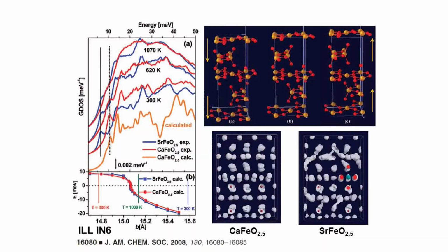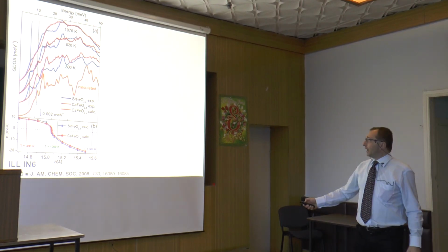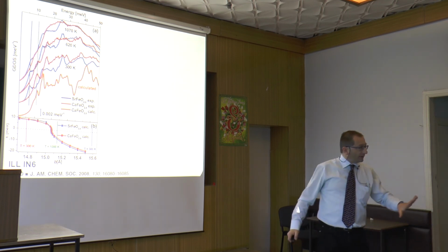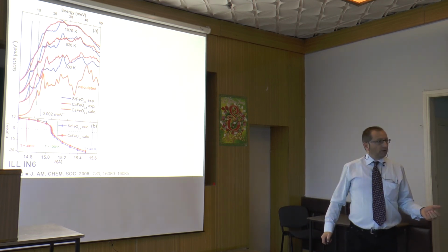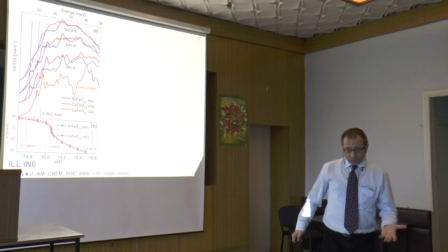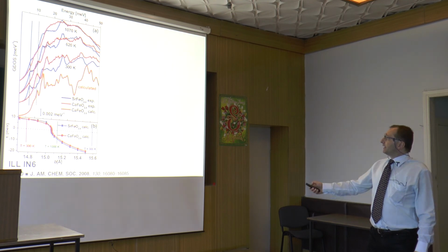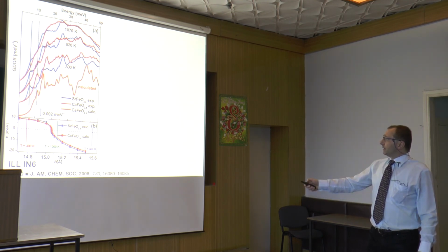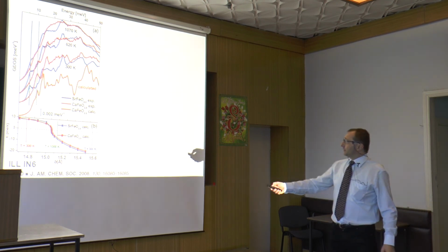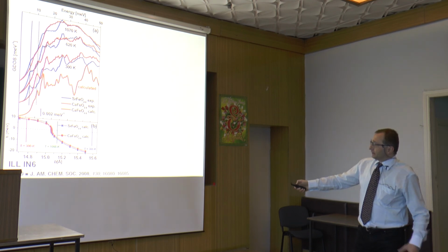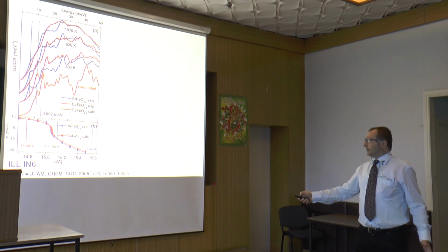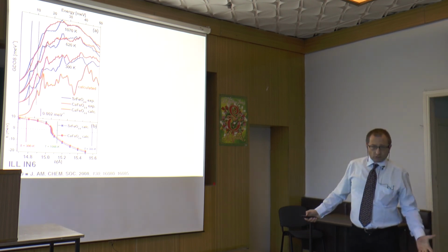If we want to see this, we need to measure phonons, and the best technique to measure phonons is inelastic neutron scattering. So we ran inelastic neutron scattering on two classes of material. The strontium iron that is able to conduct oxygen at room temperature, and the calcium iron that, although having exactly the same structure, is not able to conduct oxygen at room temperature. It must be heated at high temperature in order to work. And what we see is that at room temperature we have a soft mode at about 7.3 millielectron volt that is present in the sample that is conducting oxygen, and is not present in the sample that is not conducting.